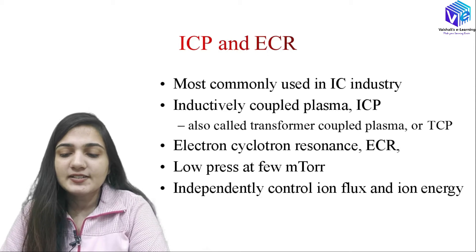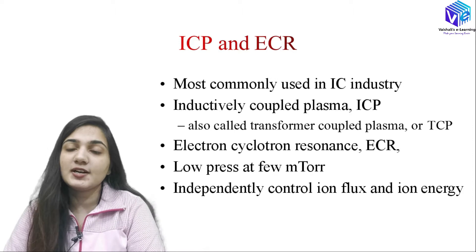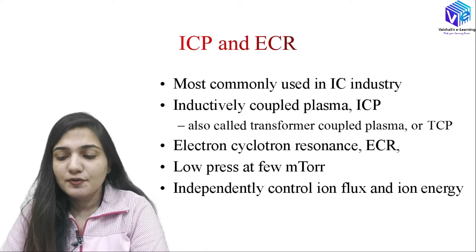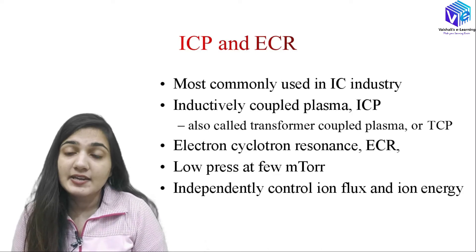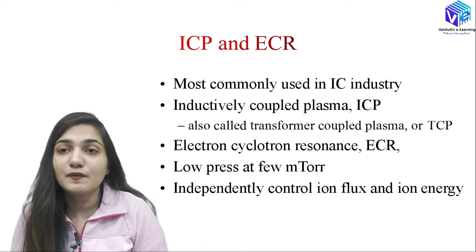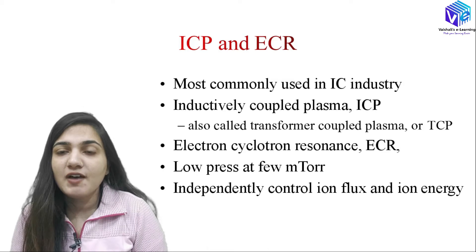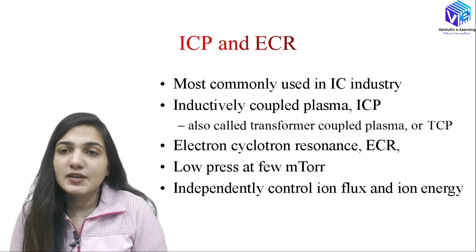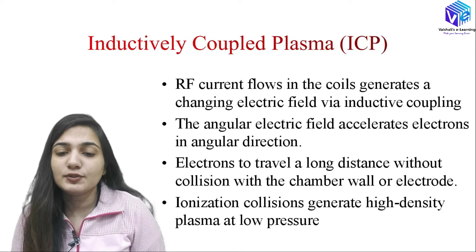ECR represents Electron Cyclotron Resonance. Both ICP and ECR operate at lower pressure conditions, in the range of a few millitorr. Both can independently control ion flux and ion energy, which is what we desire — to control the ion flux and ion energy so as to control the etching profile and the etch rate.